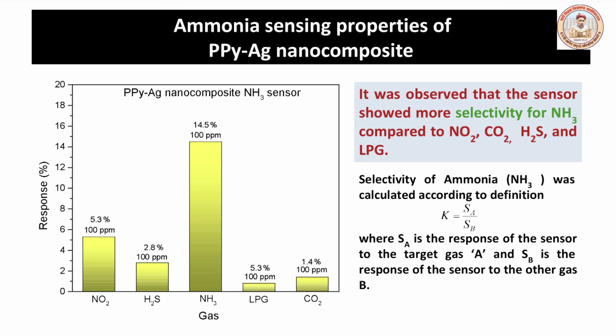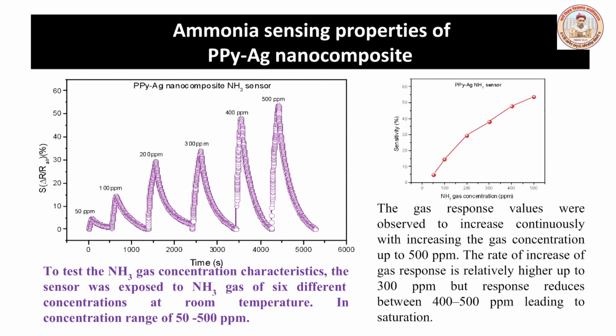Now let us discuss one of the experiments which we have performed on polypyrrole Ag nanocomposite for gas sensing. The nanocomposite was exposed to different gases at fixed 100 ppm. It was observed that sensor showed more selectivity for NH3 as compared to NO2, CO2, H2S and LPG. To test ammonia gas concentration characteristic, the sensor was exposed to ammonia gas of different concentrations at room temperature in concentration range from 50 to 500 ppm.